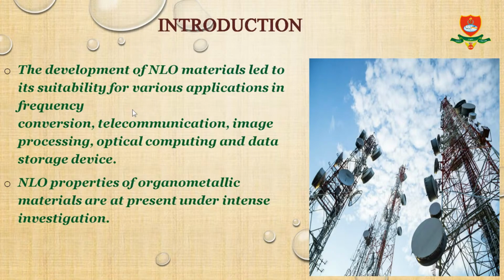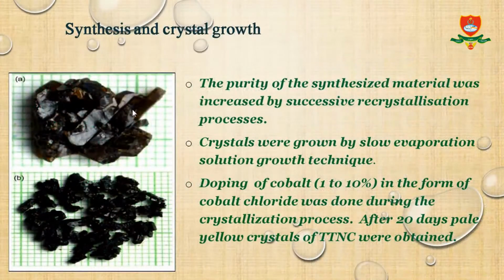NLO properties of organometallic materials are at present under intense investigation. Synthesis and crystal growth. The purity of the synthesized material was increased by successive recrystallization. Crystals were grown by the slow evaporation solution growth technique. Doping of cobalt 1 to 10% in the form of cobalt chloride was done during the crystallization process. After 20 days, pale yellow crystals of TTNC were obtained.